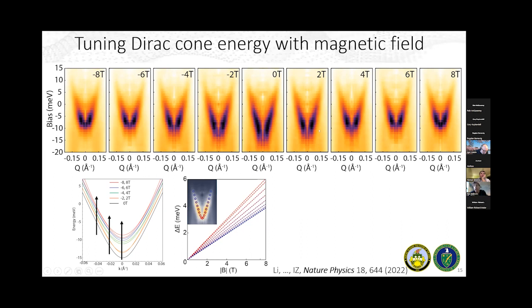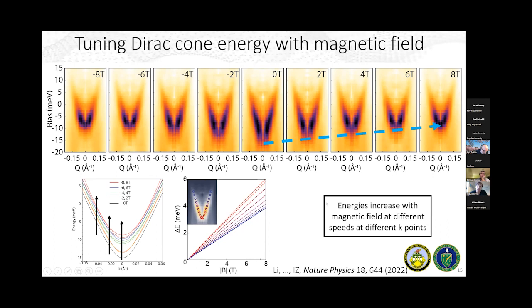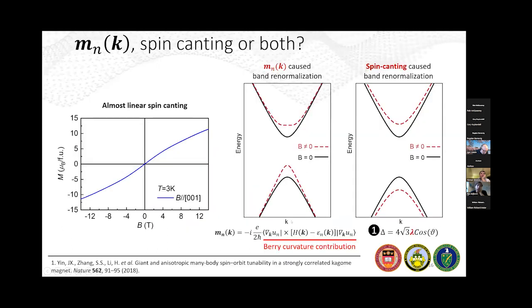The dispersion just changes, and you see more rounding of the bottom of the Dirac cone, which moves upwards. So at the very least, what you can see from this measurement is that the energy of the individual electronic states changes at different speeds for different k points. It's more substantial at the bottom of the Dirac cone.